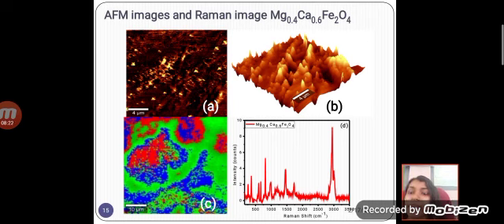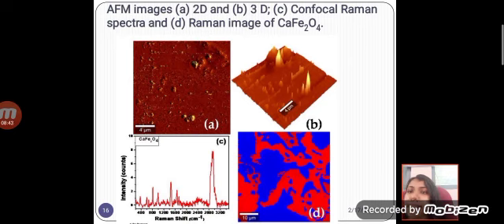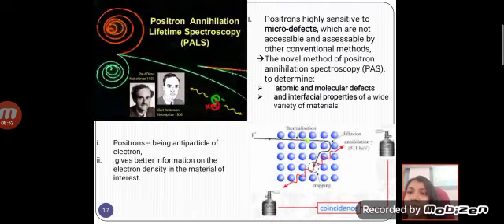And now we can see here the AFM, atomic force microscopy images, and Raman images of magnesium calcium ferrite. The topography of the samples can be seen from the AFM image, and the Raman image also shows the Raman spectra and the corresponding Raman image, or the domain mapping, of the developed samples. Here also we can see the AFM image, the three-dimensional topography, and also the confocal Raman spectra and the Raman image of calcium ferrite samples.